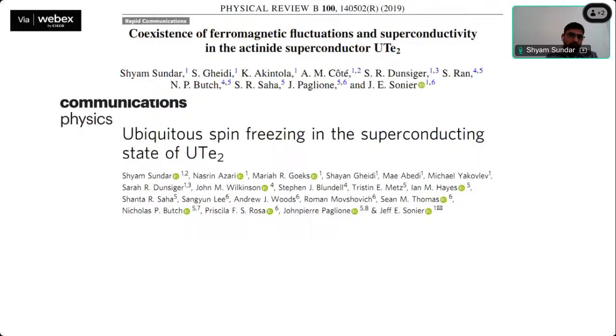And this was the very first study on this superconductor, and we found out that these single crystals are not of optimal quality. They have uranium vacancies, which are changing its magnetic landscape and its superconducting properties. So we further found out that it has a spin freezing because of those uranium vacancies. So we require a more optimal sample where they have very few uranium vacancies.